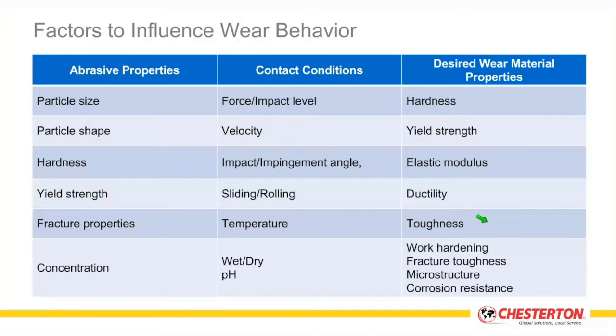Now, factors that can influence the behavior of various materials. When you're looking at the abrasive particle size, the contact condition that we're dealing with here is the force and impact at the point of contact. And there, the desired wear material property could typically be hardness. The harder the material, the better the wear resistance might be. Another example might be the opposite of that, where you're looking for more ductile applications in a high degree angle of impact, 90 degrees or so. Anywhere from, say, 75 to 90 degrees, there you might want a softer system, such as a rubber.